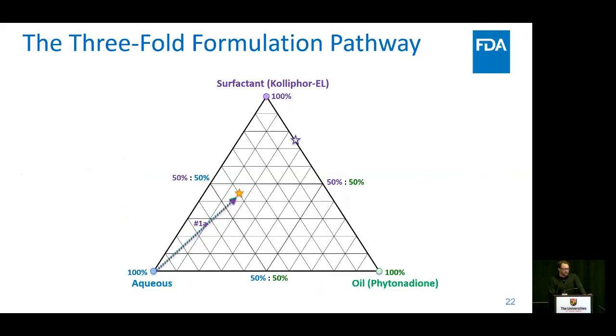And so what I showed you in the beginning is adding your organics into the aqueous. What I just showed you was adding the aqueous into the organic. And there's actually another way that you can formulate this, which is kind of a silly way to do it, but it's to take your surfactant, disperse it in the aqueous phase, and then just put the vitamin K directly in there and homogenize it.